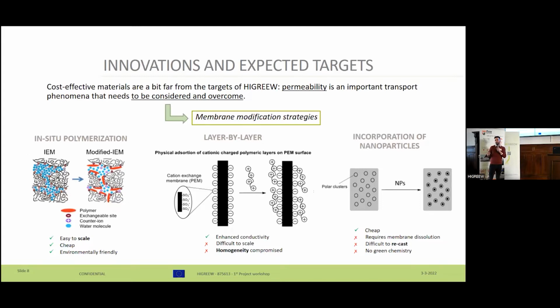These are the commercial materials that we have taken into consideration, but the cross-mixing, the crossover, is a kind of transport phenomenon that is detrimental and we should avoid. So this is a problem that needs to be considered seriously and overcome. In order to do so, we proposed different membrane modification strategies, which I'm going to explain. The first one is in situ polymerization. It consists of filling the pores and the interstices of the pristine membrane with another polymer to reduce the pore size and block or hinder the diffusion of these active species between tanks. And I have to say that this methodology is quite simple to carry out, so easy to scale, and the chemicals involved are quite cheap, as well as having low toxicity.